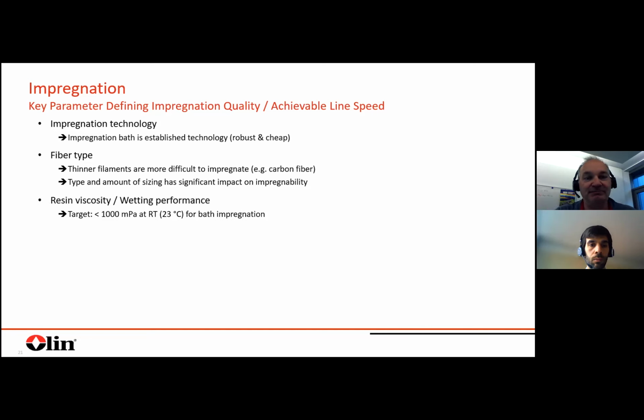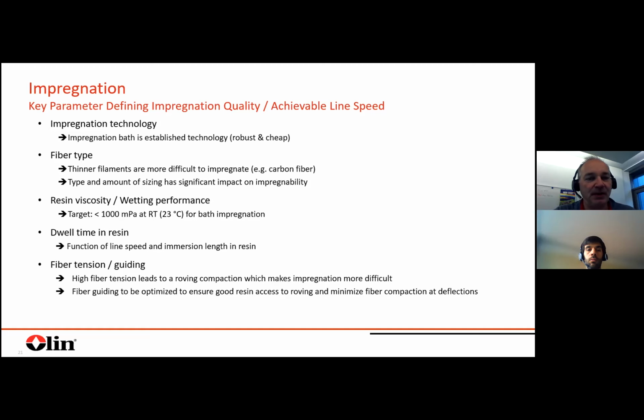For sure, the resin, no doubts. So we're targeting for pultrusion viscosities below 1000 millipascal second at room temperature for bath impregnation. The dwell time in the resin, which is a function of the line speed and the immersion length in the bath in this case. It's clear if it has more time, then you have a better impregnation usually.